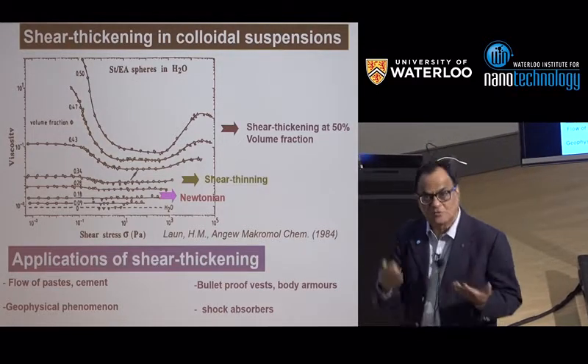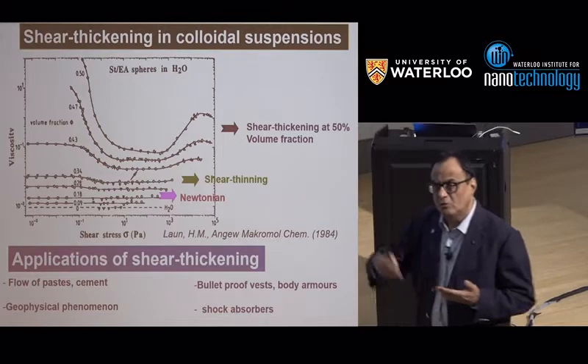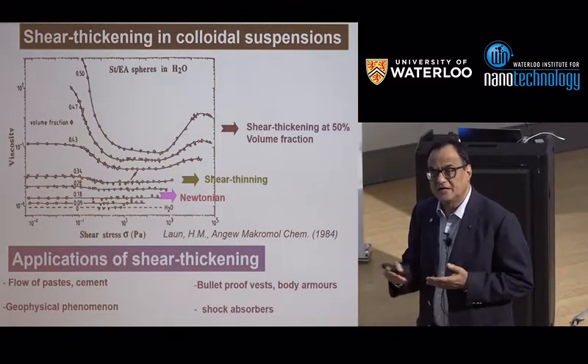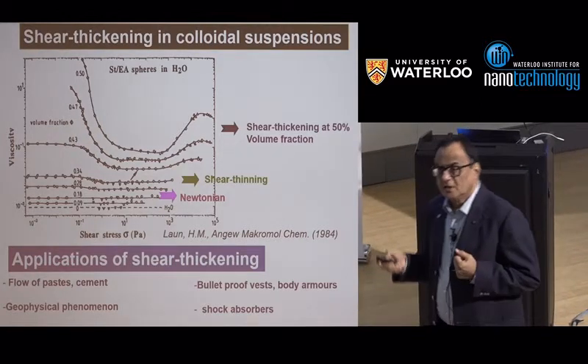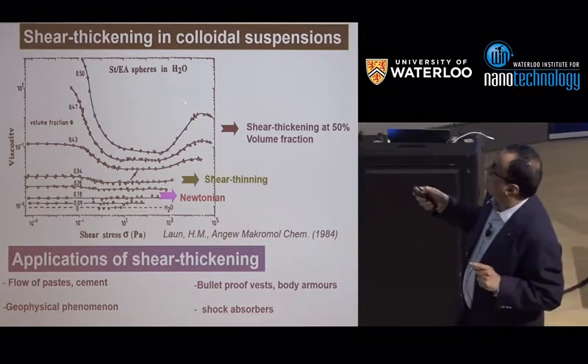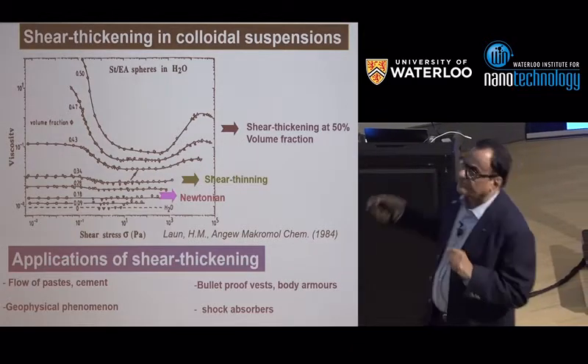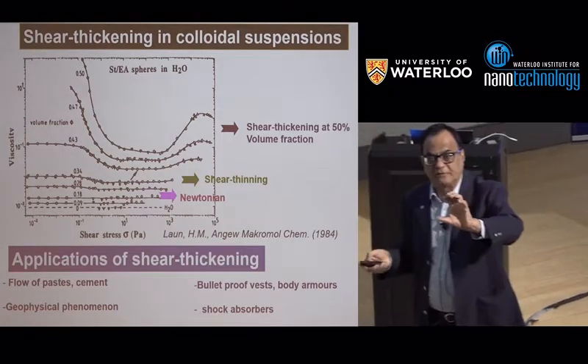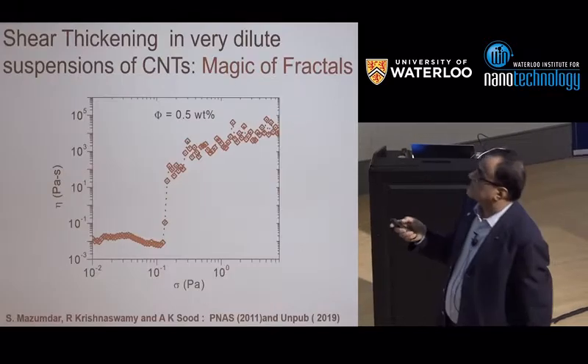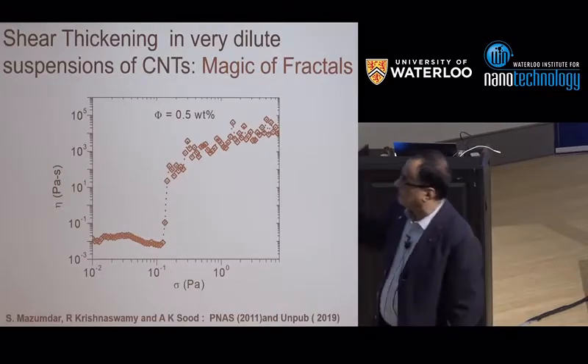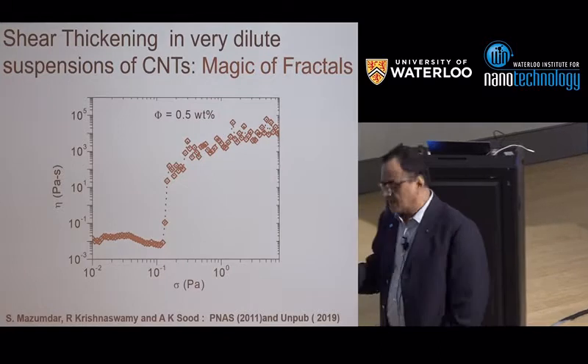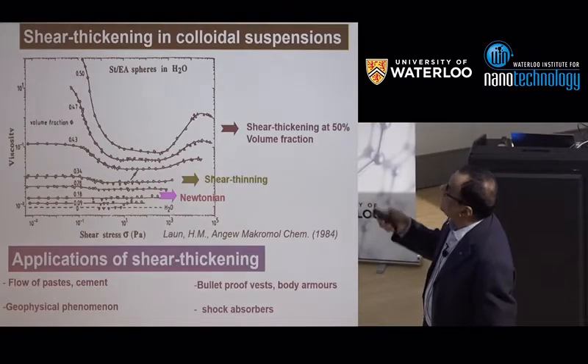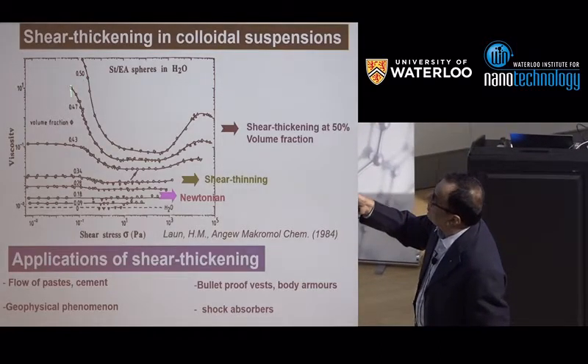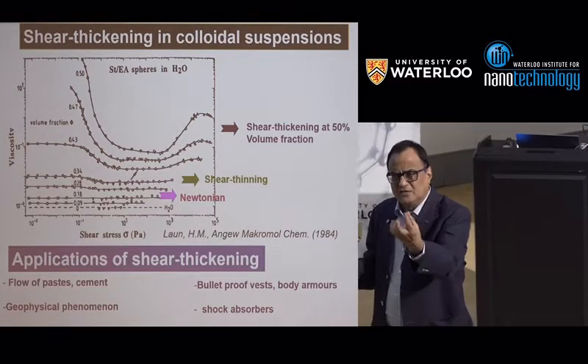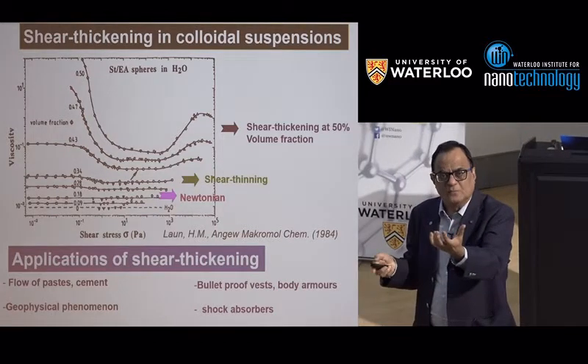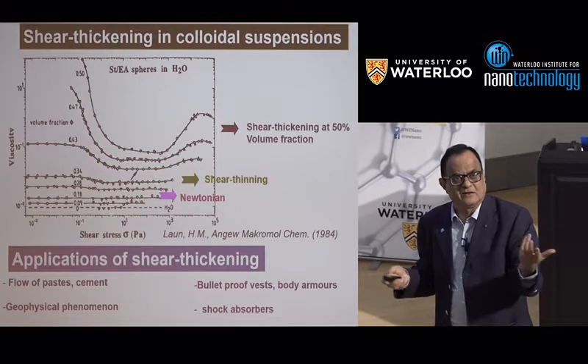So this is not only now in the lab, people are trying to translate it into applications. But the only point I want to bring out is that this is almost at 50% volume fraction of silica particles. So what we asked was, can you really decrease the volume fraction to a very small one, so that the weight of the material is very small, but still you can get shear thickening.